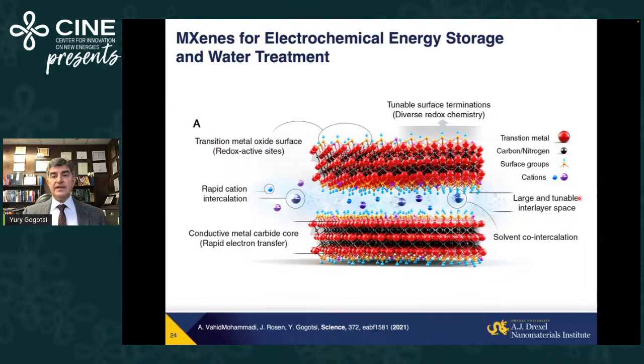Now, why are these materials attractive for electrochemical energy storage, water treatment, and other devices? This is because they have a combination of properties that make them really unique. Electronic conductivity comes from d electrons of the transition metal, with high density of states at the Fermi level and high concentration of carriers. But their surface looks like the surface of a transition metal oxide or hydroxide. Titanium, niobium, vanadium are materials used for energy storage. Those are all elements that are used in batteries, supercapacitors, and pseudocapacitors. Moreover, they have channels for transport of ions between the layers.